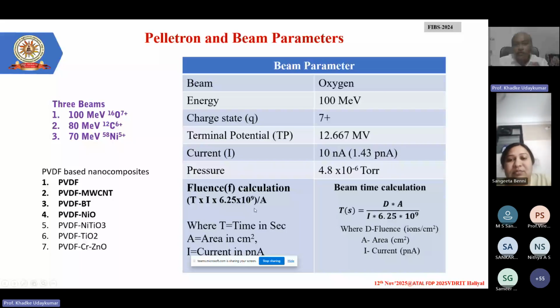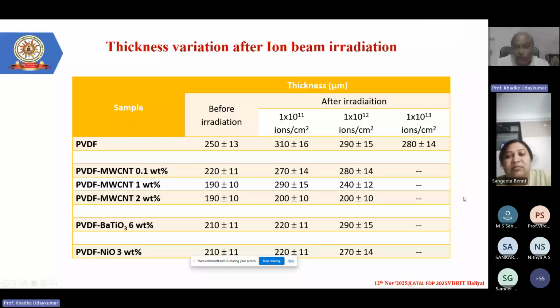Okay, what we observed the moment the beam hits the surface is that suddenly bulging of the film takes place. Now, what kind of bulging has taken place: see, pure PVDF, if we use 250 micron thickness, after bombardment with an oxygen ion beam of the order of 10 to the power 11, it has gone to 300 to 310 micron. So almost a 20% increase in the thickness has taken place.